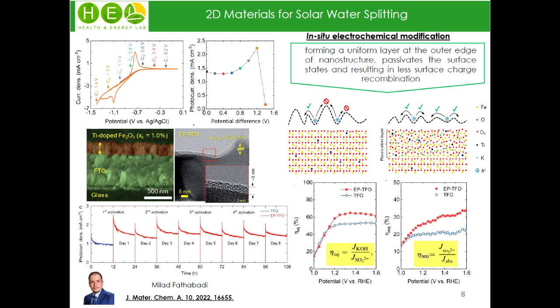Very recently, one of my students conducted research to develop in situ electrochemical modification of the surface of electrodes, in which, just before testing the photocurrent of the whole system, we sweep the surface of the electrode in a cathodic direction for a special window of potential, and realized that we could have nearly a 60% increase in the measured photocurrent.